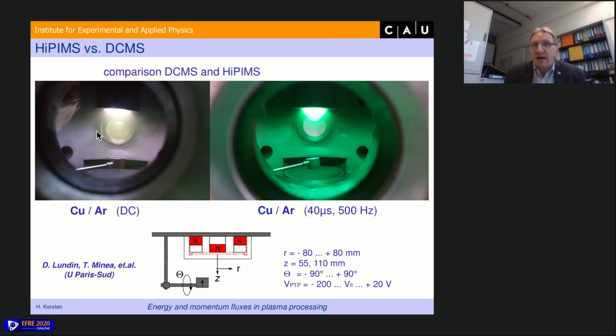Here, this is a typical argon glow, the argon plasma, and here the green color shows that there is much higher copper intensity, so it is excited copper. The copper ion lines and copper excited lines are much stronger than in this case. You can see it is at the same pressure and at the same power, but here you have a much higher metallic sputtering part.